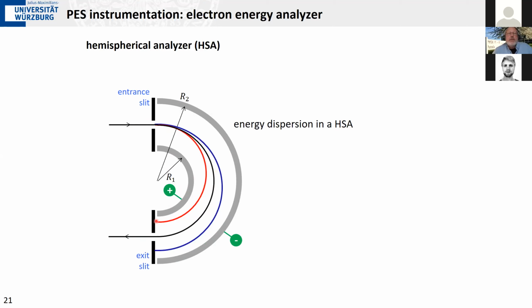So you can think of it just as in an optical spectrometer. And electrons that are too fast will not be bent as strongly as the electrons that have the pass energy, and they will hit this wall and will also not hit the exit slit. And by this, you filter out a defined energy, and then you can measure the amount of photoelectrons at this energy. And in order to measure other energies, you decelerate the electron beam hitting the entrance slit, or you accelerate them, and by that you can scan the entire energy range.